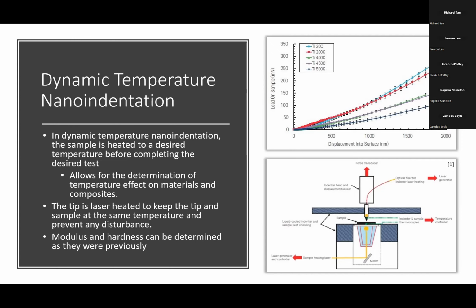This allows you to have these dynamic temperature measurements, and using it, you still have the same methods of finding the modulus and hardness with these dynamic temperature tests. The top graph here is an example of a heated up titanium sample, ranging from 20 degrees C to 500 degrees C. We can see that the slope decreases as your temperature increases, showing that the unloading stiffness on these samples also is decreasing.